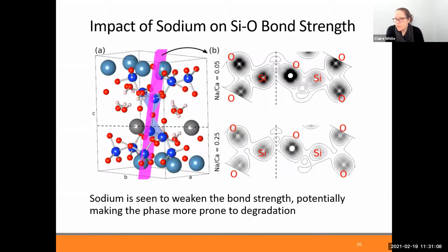We also went on and did analysis of the structures themselves at different sodium incorporation amounts. I'm not going to show a lot of what we did, but for example, here we looked at the electron density contour maps of the bonding between silicate tetrahedra and how sodium in the vicinity of these silicate tetrahedra is affecting the electron densities. At small amounts of sodium, there tends to be quite strong bonding still occurring between the silicate tetrahedra. But if we go to really high levels of sodium, the contour maps show that bonding strength has weakened. That's potentially one of the reasons why really high sodium levels are not so great in these phases. We also looked at things like barriers for movement of sodium through the system and some other properties to get a sense of sodium's impact on the material.